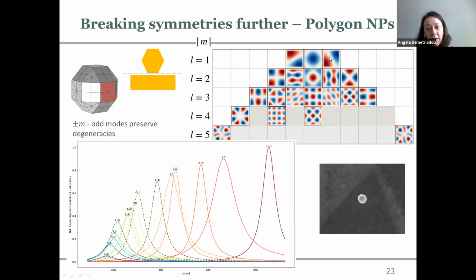And the reason that they keep their degeneracy is because if you look around this facet, you still have a symmetry on this plane and that plane there. So you have 4 square facets surrounding this square facet itself. So there is some symmetry remaining in this system.